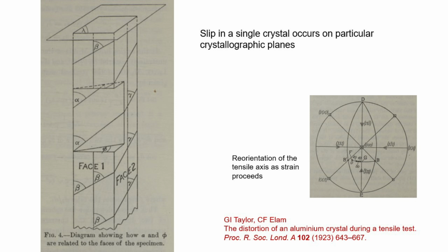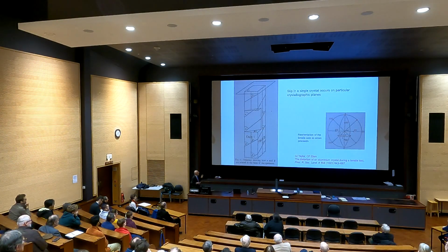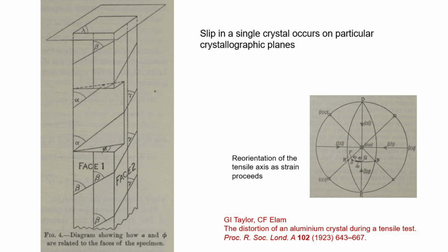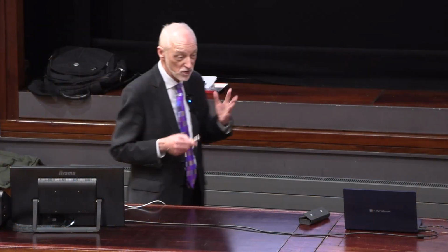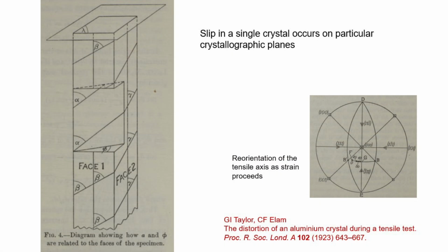And here are a couple of pictures from their paper. So this is a schematic of one of these single crystals. Astonishing feat of crystal making. These, in the real world, were square cross-section bars, where the sides of the cross-section were 1 centimeter, and the length of the crystal was 20 centimeters. Astonishing, single crystal. And the way they were made meant that you got a random crystal orientation every time. That, in one sense, was awkward, but in another sense, wonderful, because it enabled you to test the effect of angle with every experiment you did. And of course, that then meant relating the sides of the crystal to the angle of those crystal planes. And I put in this diagram just for the amusement of some in the audience who've had to go through all of this in their undergraduate lectures of tensile axis moving towards whatever in these stereographic projections. They needed to use those to understand what was going on.